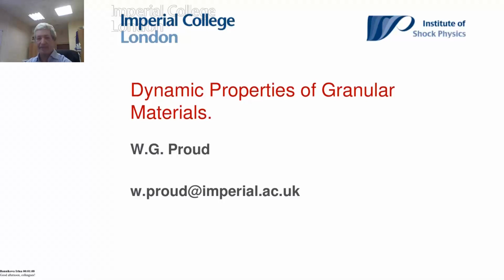Okay, great. No, that would be fantastic. I look forward to reading those papers, seeing in more detail what you're doing. But certainly, I would say notch testing in these materials is yet another area. Even with ceramic notch tests, the American standards for ceramic testing do notch tests, but they find just experimental things like using a razor blade or a really sharp metal surface. You have to scratch down the notch in order to get reproducible results, and that's because they need to put in some very precise initial micro damage into the notch in the specimen. So I think those type of variations are quite important to understand. So yeah, absolutely, that sounds like a good thing to do.